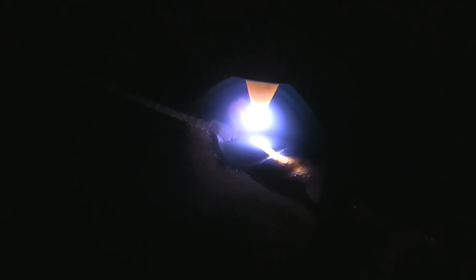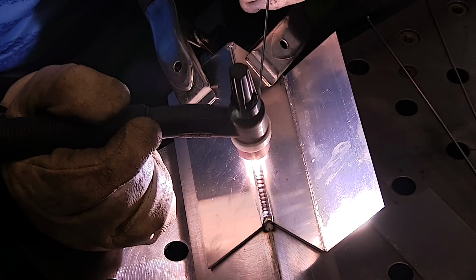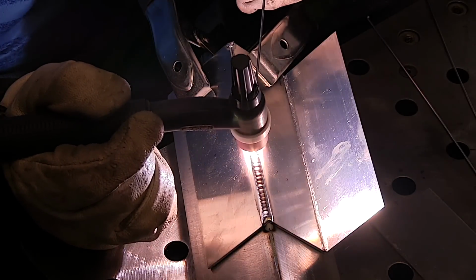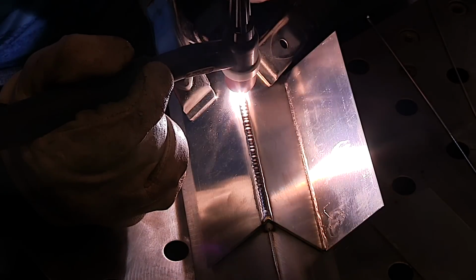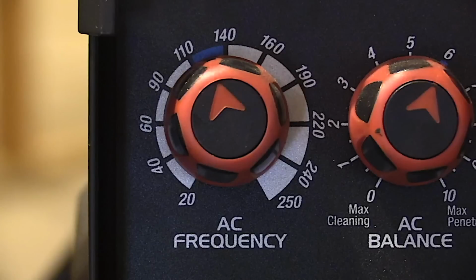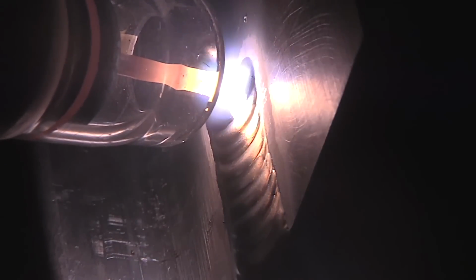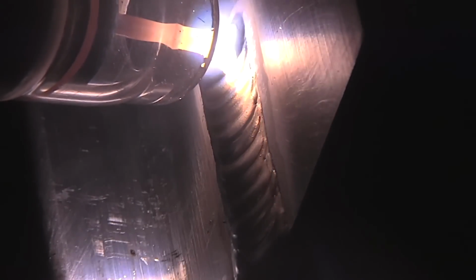And I do like to use a tapered tip on this thickness aluminum and thinner. I get a nice crisp low amperage arc start with a tapered tip, and at 110 Hertz, anywhere from 110 to 140 is a really good setting for this. It gives you a lot of arc control, very little arc wander on the start with that tapered tip, and it kind of helps narrow the bead a little bit if that's what you're after. A setting of 120 Hertz on the AC frequency is a really good all-around setting if you just want to set it and forget it until you get to something really thick.